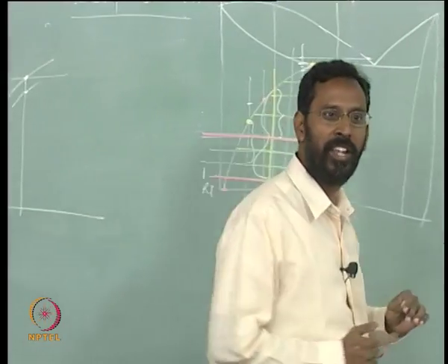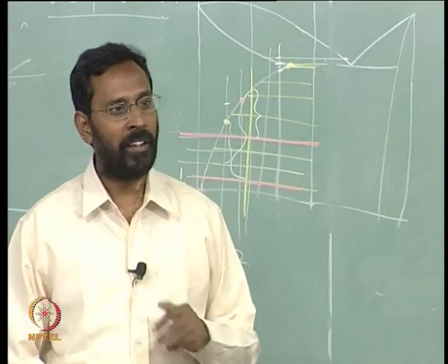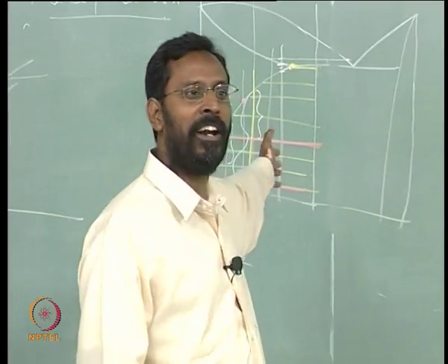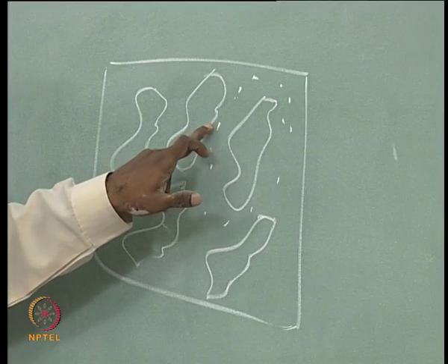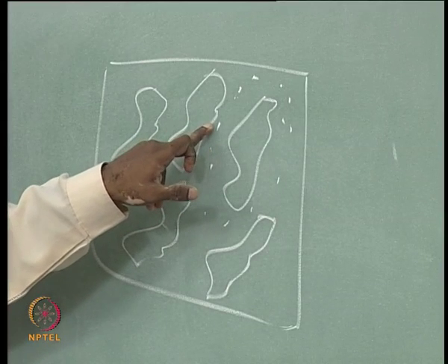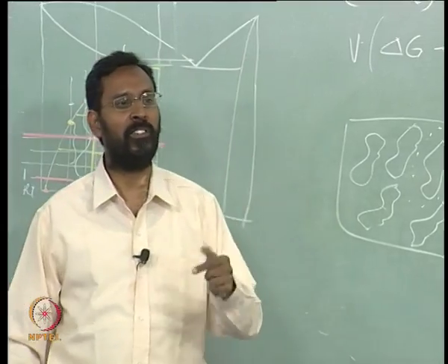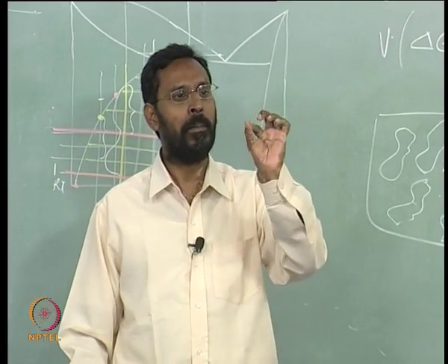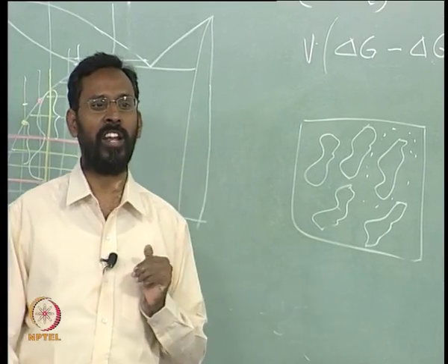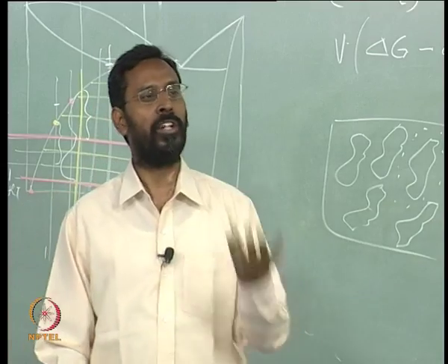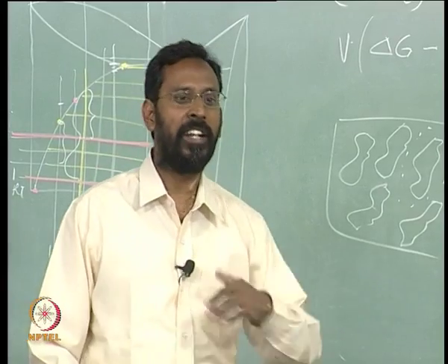That is where people have seen that if it is a hypoeutectic or a hypereutectic, life is very easy. If it is a hypoeutectic, you already have alpha dendrites. So when the eutectic mixture is forming, the nucleation can occur on the alpha which is already there, and it will be the alpha of the eutectic mixture which nucleates first. And the moment alpha forms, because alpha is a pure aluminum kind of composition, the regions next to it become rich in copper, so theta comes out. So it is like one follows the other, the theta follows the alpha.